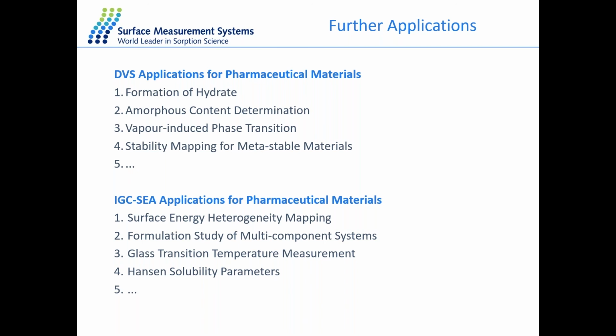And in the pharmaceutical industry, we do have lots of different applications with both of the techniques. So for example, DVS can also be used to determine the formation of hydrate, the kinetics of this formation, as well as the structure of this hydrate. As well as with some organic vapor, we can determine the amorphous content and the stability of certain materials at a certain condition. And the IGC technique is more widely used for the formulation design in pharmaceutical materials. So for example, the carrier and the API, the affinity with each other, and also the blending performance or behavior between different components in this system, or in the case of the coating of a polymer on the base material, what's the affinity between each other, and that could be correlated with the surface energy value of each individual component.